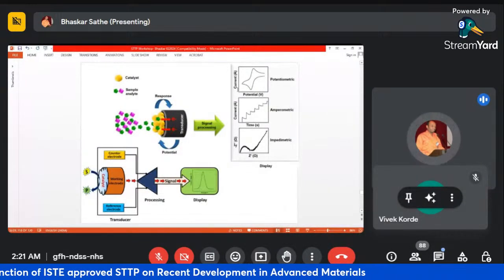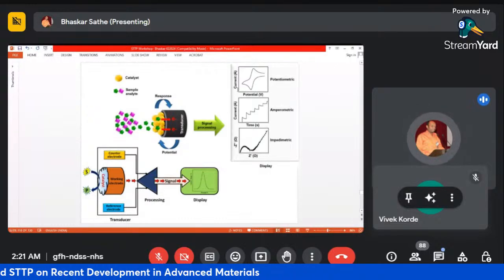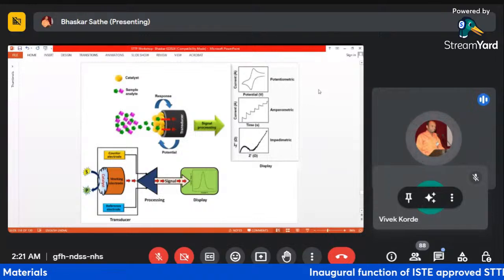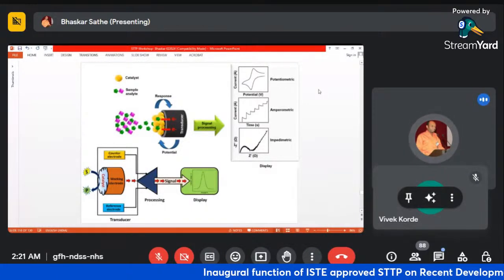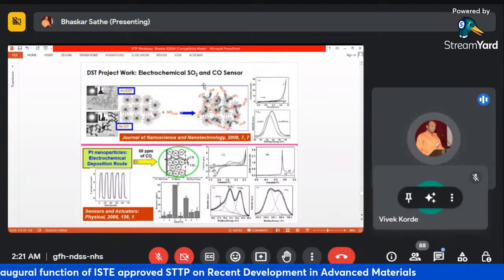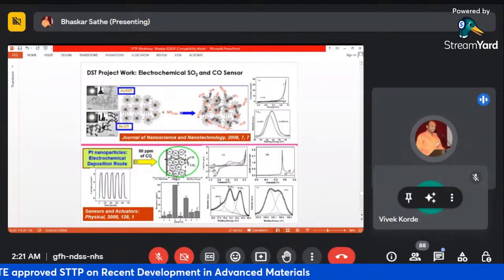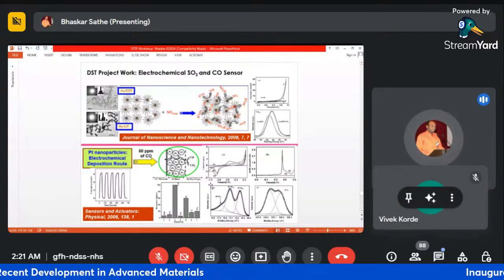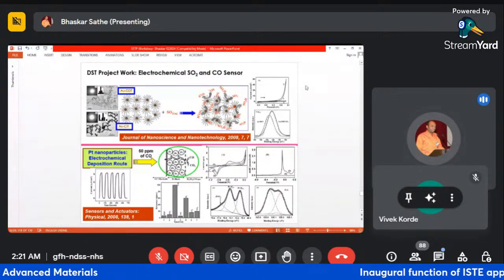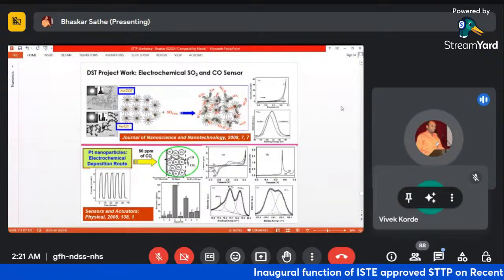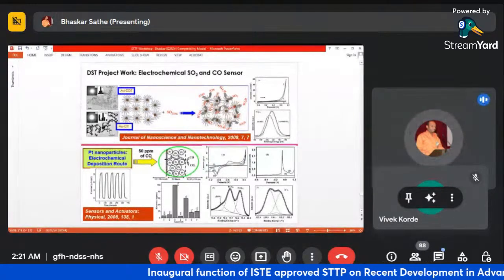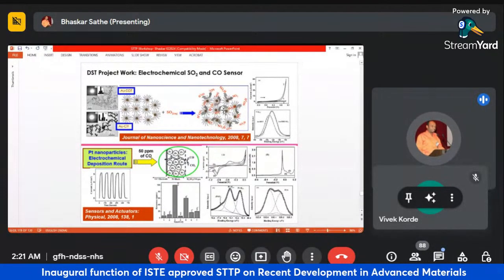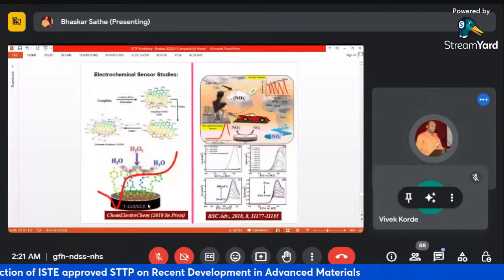In another case, sensing, this advanced material we can use for sensing purposes, electrochemical sensing, where potentiometric, amperometric, and impedimetric methods can be done, where the signal is proportional to the concentration of the gas. Here we have used a sulfur dioxide gas sensor. Another system, a platinum based system, we have used for carbon monoxide. These two are harmful gases which you observe in the industrial zone. So we can do this, one on gold nanoparticles, another on platinum nanoparticles.